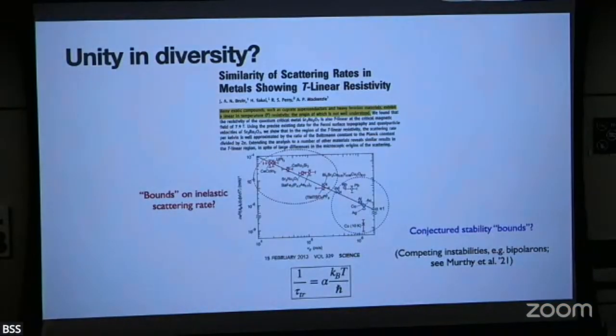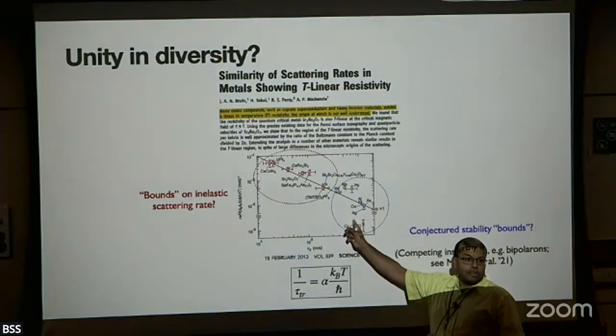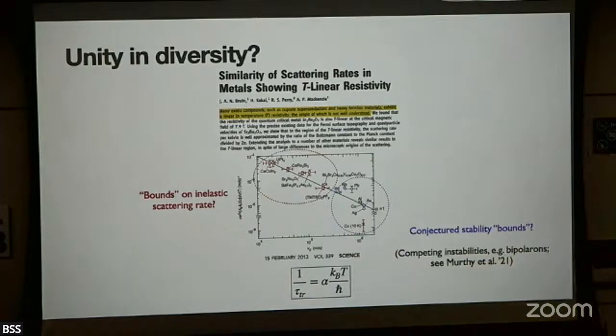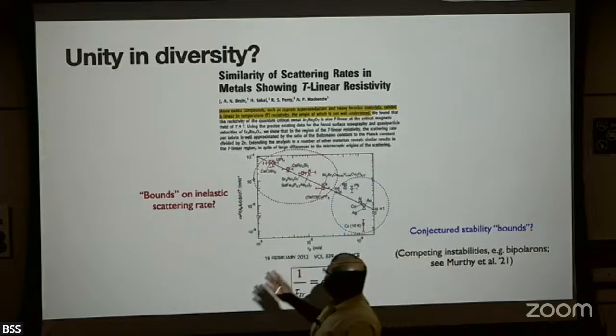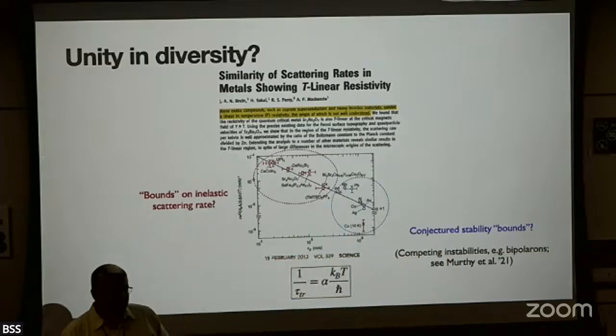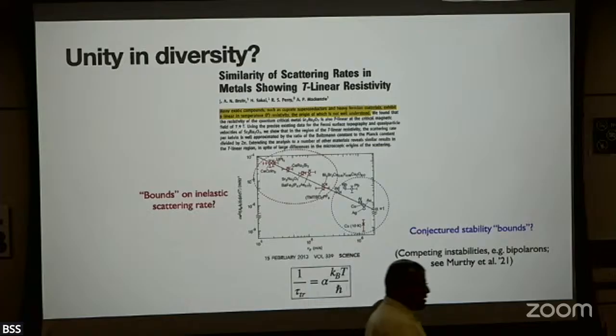Of course, one of the greatest tragedies of this interesting regime of T-linear resistivity is, again, the fact that electron-phonon scattering also gives you the same power law. And all these simple metals that you see up there, copper, silver, gold, they also have a Planckian scattering. By the way, this is something that was appreciated by Pippard in the 30s. So there seems to be something interesting going on. And the question is, what can we say about it?